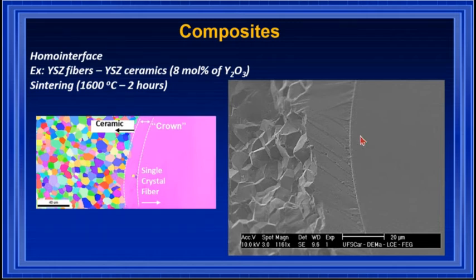We can see from the EBSD analysis that in the ceramics you don't have any texture, so we have all crystal orientations from the yttrium stabilized zirconia. But here in the crystal, of course, we have just one orientation. What was interesting is that during the sintering process, an epitaxial growth occurs at the surface of the fiber, and we can see that we generate here also a single crystal that we call the interface between the two, the ceramic and crystal.